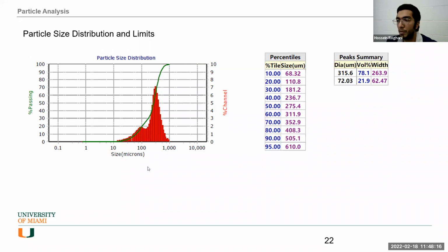Here is a measurement I did maybe 1 month ago for a sand-coated rebar, which shows the particle distribution. You can see two normal distributions beside each other, a smaller peak and a higher peak, because in the resin they do not really use neat resin. So in the resin you have some other particles that are not sand. The sand is on the surface and is larger, but there are some particles in your resin that are not sand, and when you put the entire thing inside the particle size analyzer, it gives you the entire thing. So we can consider that part as noise. If we have those limits for the particles in the resin, we can omit them and come up with the particle size distribution of the sand, which can give us a better idea of the surface roughness.